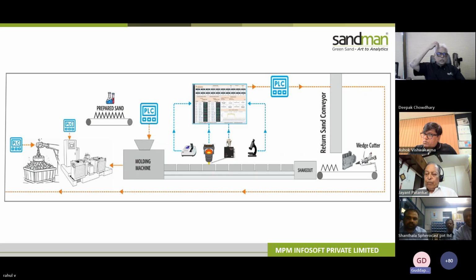Okay, thank you, sir. One more question. What may be the cause for open grains and shrinkage below the risers, especially in casting? Actually, the two situations are contrary to each other. Open grains are caused by higher carbon and higher carbon equivalent, and the shrinkage below the riser is caused by lower carbon equivalent and lower carbon.